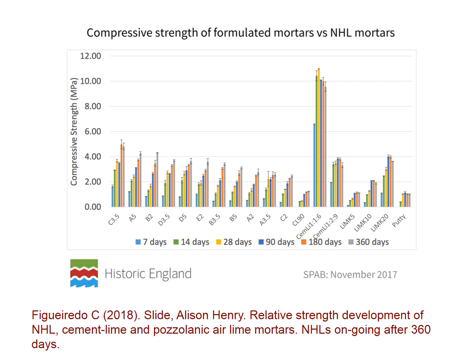The Canadian conservation mix, if you like, is 1, 2.5, 8, and that does take account of the ever strengthening nature of Portland cements. Equally, the metakaolin gauged pozzolanic mixes made with lime, they too have reached their maximum strength after about 3 months.